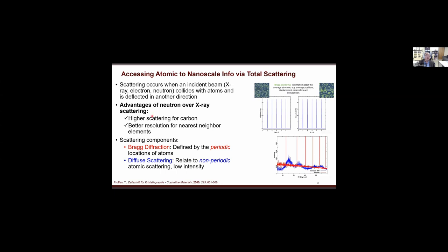that. However, when you have an amorphous or near amorphous material, you have this advantage of using neutron over X-ray scattering: you have higher scattering for carbon, because you have a MOF-derived carbon material, and better resolution for nearest neighbor elements. And then the scattering components: we have the periodic part, which is the Bragg scattering, and the non-periodic part, the diffuse scattering, which normally has no intensity. But here, it actually plays a very significant role, as we can see later for the data fitting.